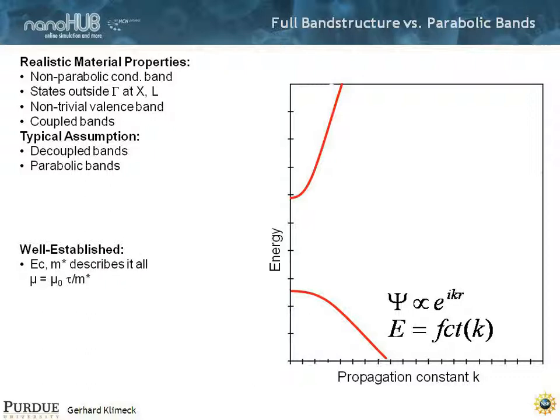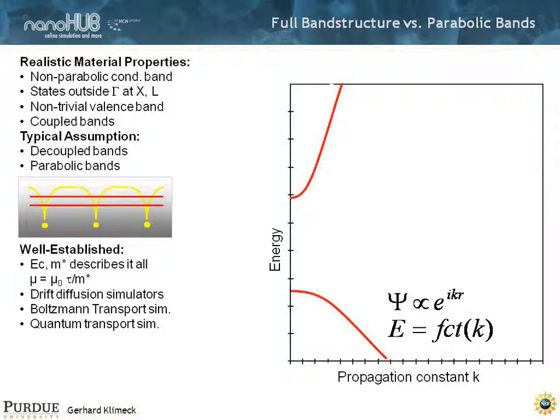We place a parabolic band up in the conduction band and we forget about all of these other bands. We say, I have a conduction band, an effective mass, a mu. And after that, I just work in these concepts, and I can build all kinds of complicated simulation tools in drift diffusion, in Boltzmann, even quantum transport simulations. Most quantum transport simulators that I'm aware of start from the base assumption of there's a conduction band edge and an M-star. Everything else is parabolic. And the focal point of this presentation is how that breaks down, how that does not work for quantitative device engineering at resonant tunneling diodes at the nanometer scale. It breaks down because the bands are coupled and there's material variations on the nanometer scale.